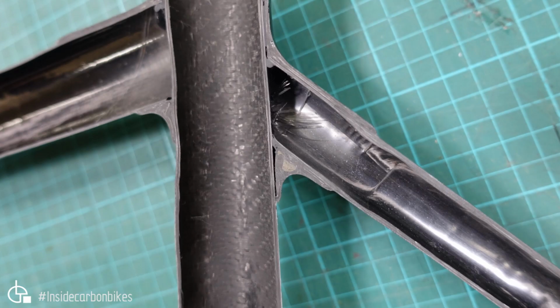So that's a bit of a concern with that one there. Here's another view, and yeah, you can really see that void. It is just closed off right at the end here, so it's not fully open to edge. And then this one here has just a filler of adhesive spew out. Otherwise it would be open to edge as well. You can also see some light porosity and some filler in this area here. Yeah, so no voids to the seat stay bond, but quite substantial to the seat tube. So that's not great.